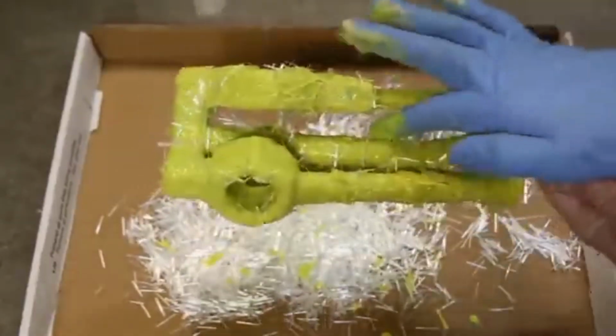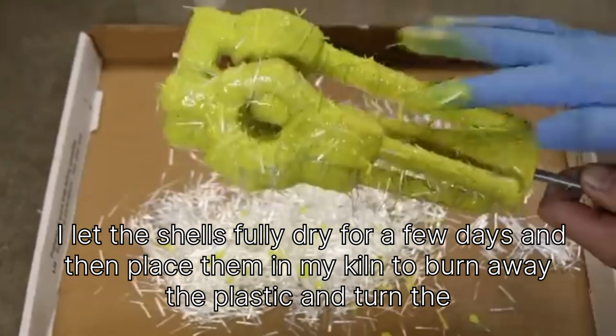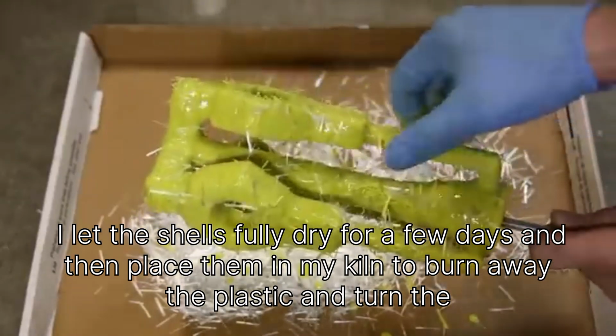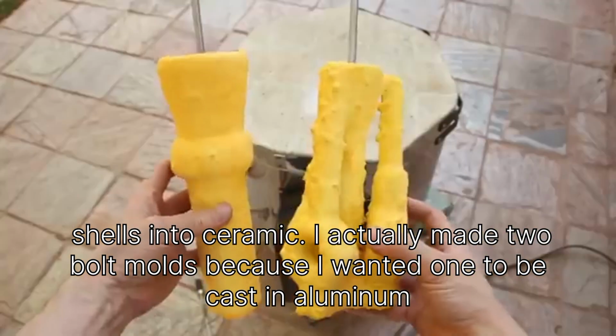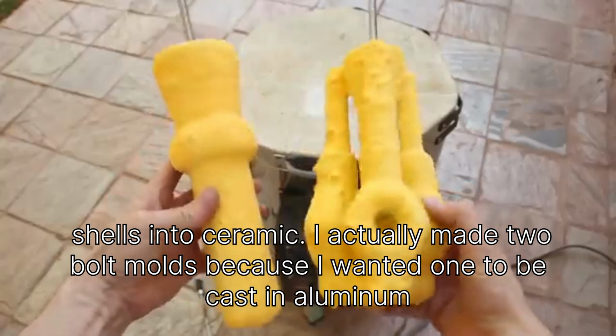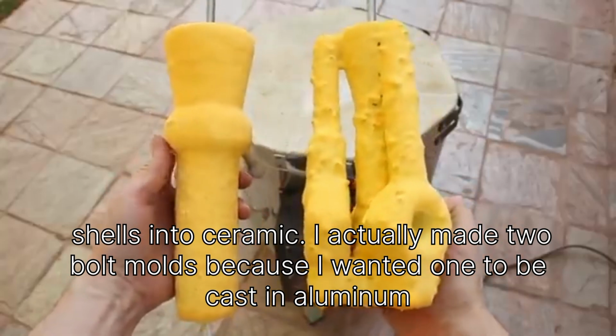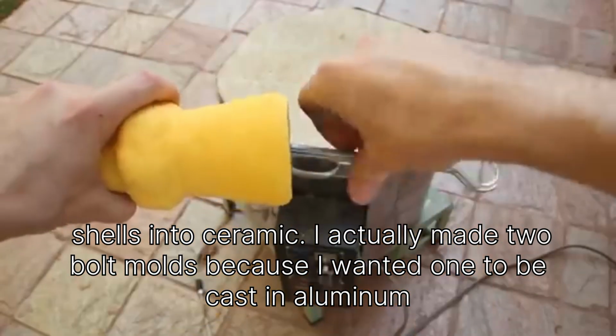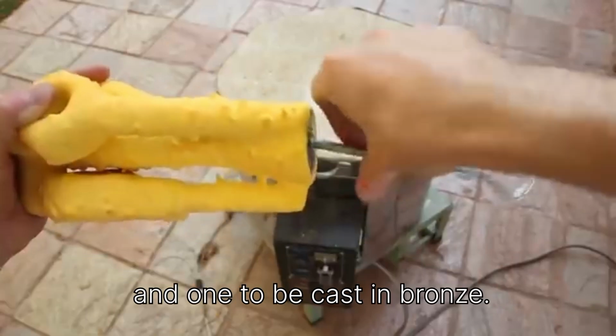I let the shells fully dry for a few days and then placed them in my kiln to burn away the plastic and turn the shells into ceramic. I actually made 2 bolt molds because I wanted one to be cast in aluminum and one to be cast in bronze.